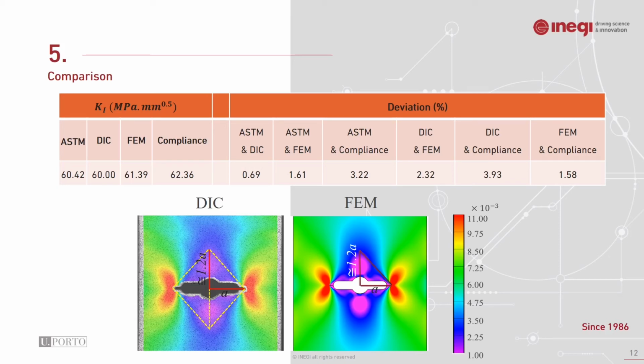Moreover, it is possible to focus on the stress dead zone characteristic, as it was beta, and in the literature it was reported as 1.2a. So the figure is showing the strain field. The crack tip accounted for the maximum strain. I'm talking about the kidney shape, verified from both digital image correlation and finite element method. And the triangular region is the dead zone with a height of 1.2a. So the strain field validated the characteristic of the dead zone both in shape and in quantity.